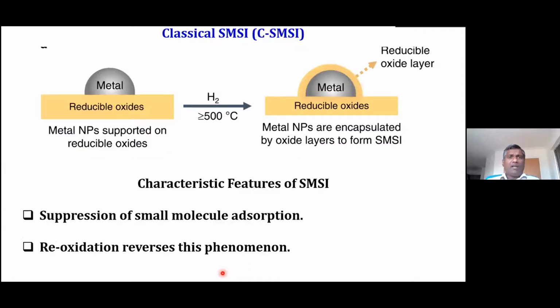Okay. Now, this is classical SMSI. So when you have a reducible metal oxide and you have a metal, when you hydrogenate this catalyst, say around 500, or sometimes slightly less than 500, what you get is a support layer on the metal nanoparticles.